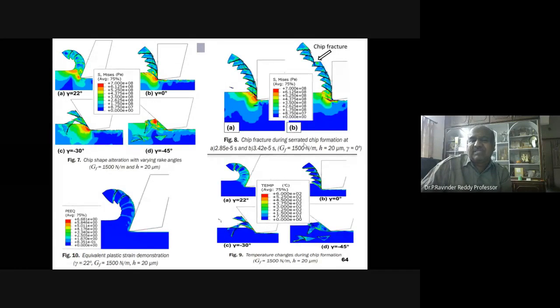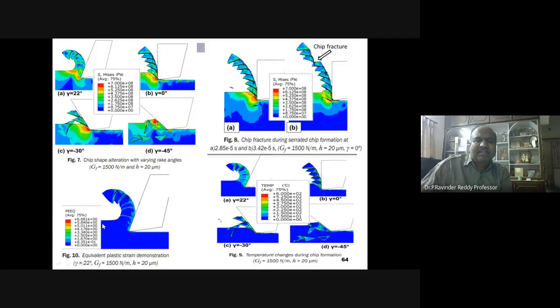And again, here you can see chip fracture during serrated chip formation at different strains. So you can find chip fracture taking place, and there is going to be a connection here. Because here, a rake angle of 22 degrees is fine. Keeping 22 degrees, energy of 1500 is fine, and a depth of cut of 20 microns is fine.